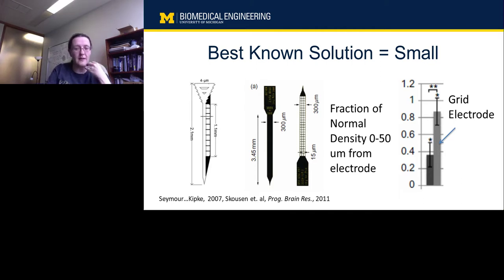And what they found is that the number of neurons surrounding the electrode was much, much higher around these small elements. For example, taking this from Skousen et al., around the 15 micron lattice elements, there was 85% of normal neuron density, compared to the solid part of the electrode, where there was only 35% normal neuron density, which was pretty typical for a probe. So this is an enormous effect. There are 50% more of the neurons that we're missing around these small elements. And this really suggests that what we should be doing is making these electrodes very, very small.